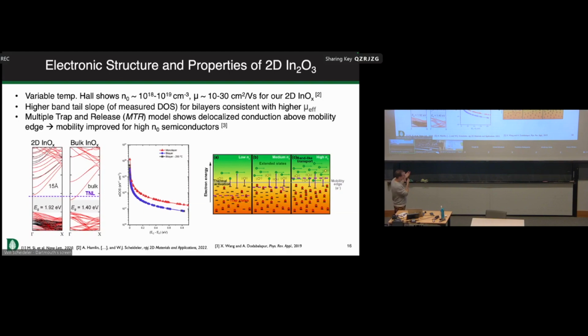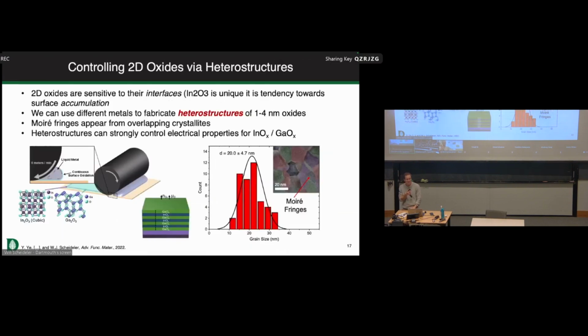There's also some interesting work, I'll point out, in the indium oxide space more recently on highly scaled devices that has shown that, if you do DFT on a very thin slab of indium oxide, it looks significantly different than the bulk. You essentially can shift that fundamental band gap of the indium oxide by about half an eV. So that's actually what we're taking advantage of when we make these materials that we can electrostatically gate.